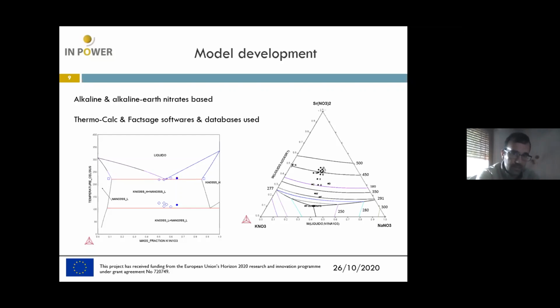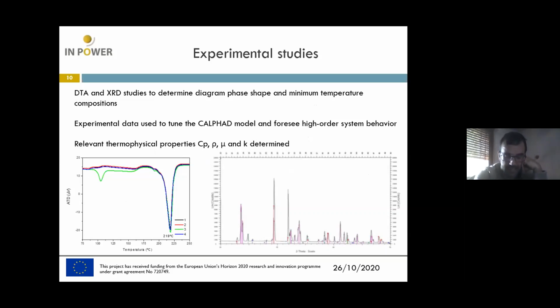Here in this slide, you can see the well-known sodium potassium nitrate phase diagram, and on the right you can see one of the ternary diagrams with strontium nitrate, which was one of the other materials of the quaternary system. And in this case, for example, in this ternary diagram, the eutectic composition melting temperature was about 210 degrees. This thermodynamic assessment cannot be done without experimental studies.